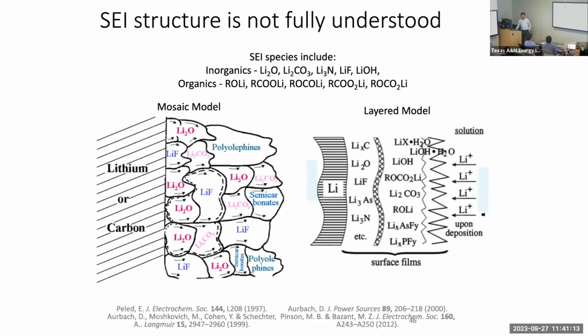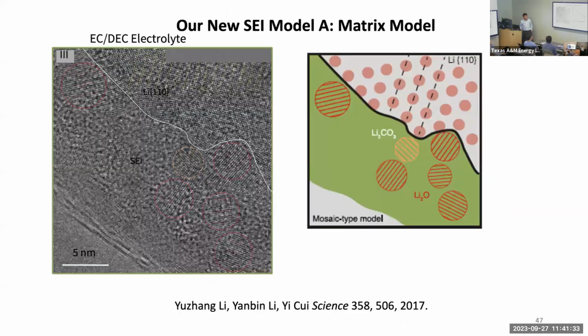right? So then we also saw for the first time, on any anode surface, this layer, SEI, solid electrolyte interphase, so important. When you're charging and discharging, efficiency needs to be high, and it determines to a very large extent your safety performance and so on. Nobody understands the structure. There's a lot of debate. So we were able to image it for the first time. This is a layer about 20 nanometers thick of solid electrolyte interphase. It consists of inorganic particles, mostly lithium oxide, embedded in an amorphous matrix.